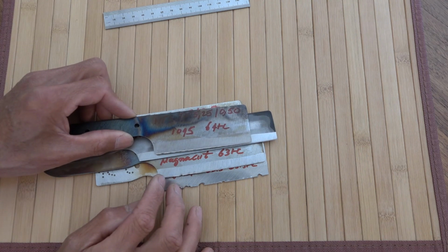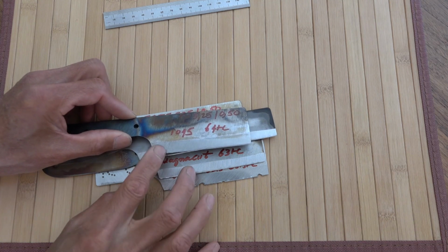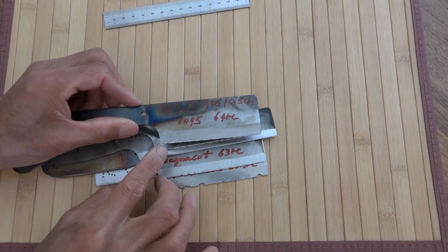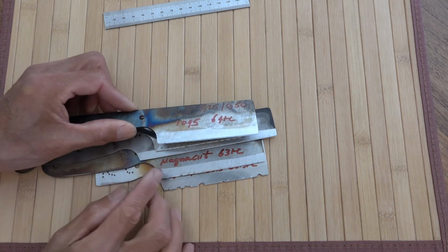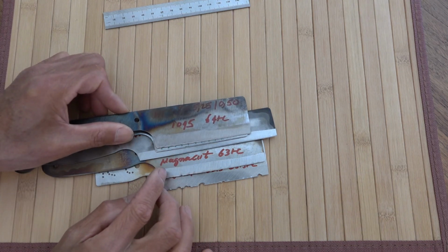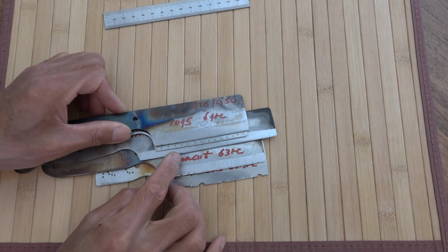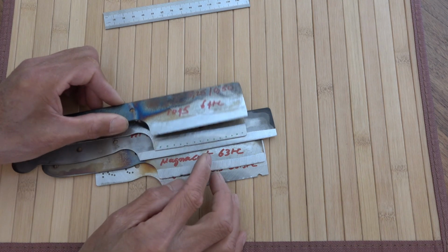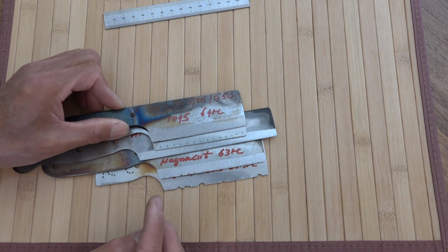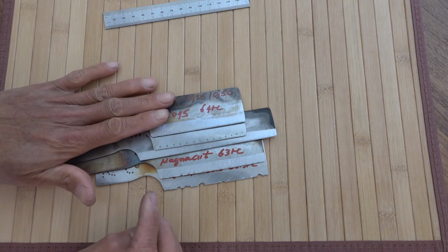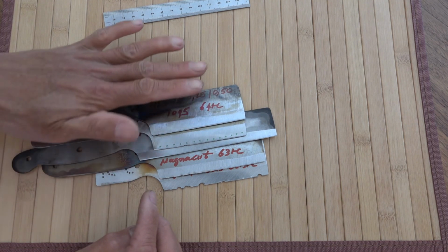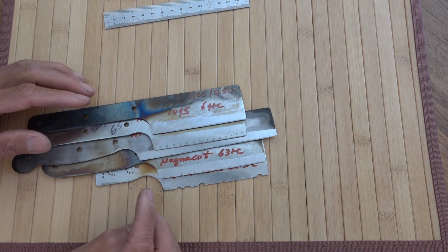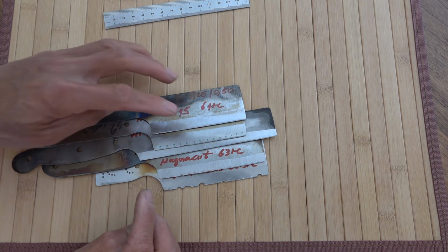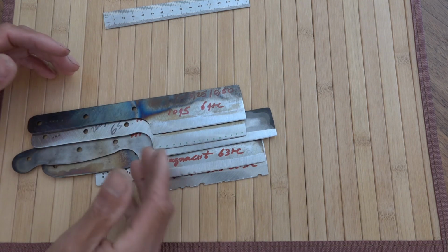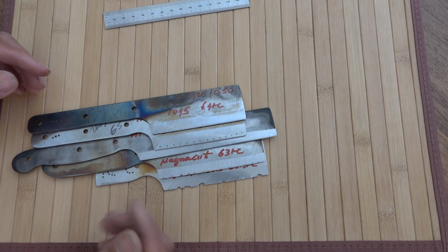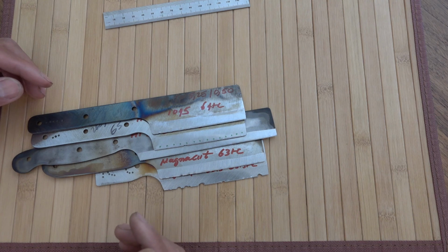This is 1095 at 64 Rockwell, and this is a dent, a deflection, and it did better than 26C3 at 65. This is 64 Rockwell. And so the edge stability of the 1095 is actually really excellent. And as I said, CPM 154 is actually the most surprising among these steels.